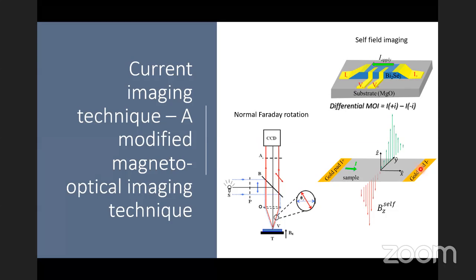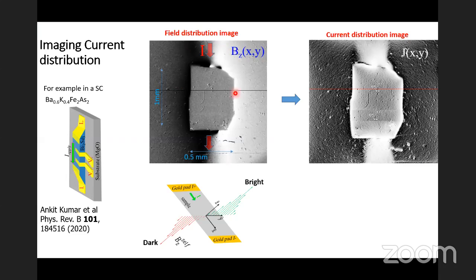So let me give you an example. It's not in a topological insulator, but it is an example. What you see here is a half a millimeter crystal of a superconductor, and you have contacts which are sending in current. And this is the image of the field Bz(x,y), the magnetic field distribution which is generated by the current. You can see that there is a bright region and there is a dark region in this image. The bright region corresponds to the positive part of the self field generated by the current, and the dark region is the negative part, namely the field which is going into the plane of the surface. The field that is coming out is bright and the field that is going in is dark. And so typical current images look like this. They will have a bright and dark contrast.